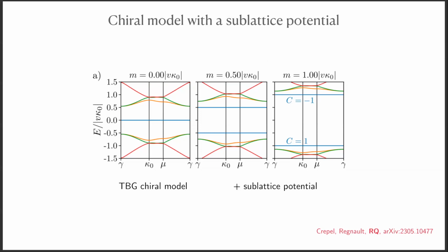So we start exactly with the model for the TBG. But now we know there's a disbalance between the A and the B sublattice, right? So I just do that. I put in an additional mass that shifts the A sublattice and the B sublattice, and therefore creates a mass gap. And that's maybe a little bit of a silly thing to do. It's very similar to TBG, this graphene aligned with the hBN. You also break that symmetry, you create a little mass gap, that will be this mass gap.